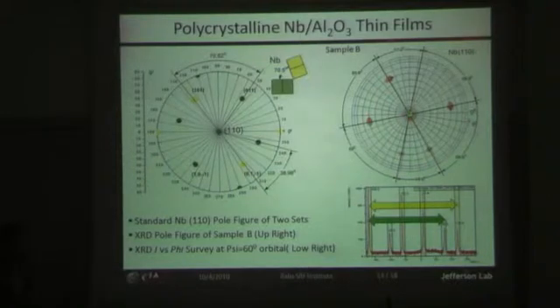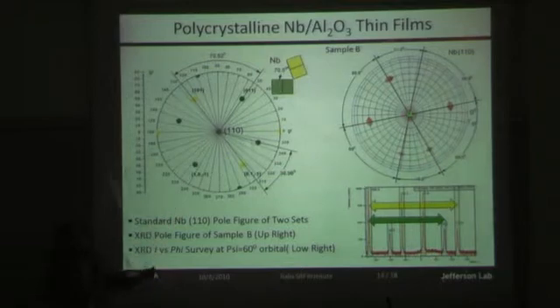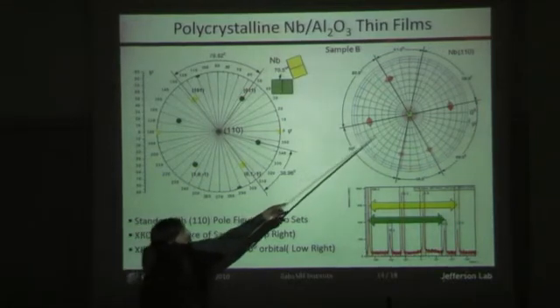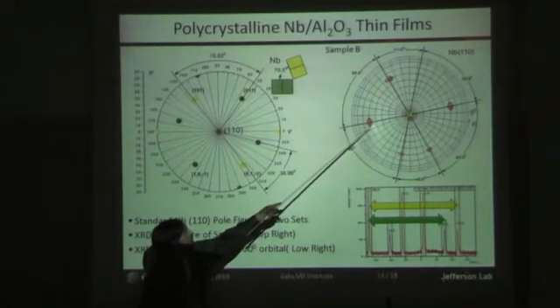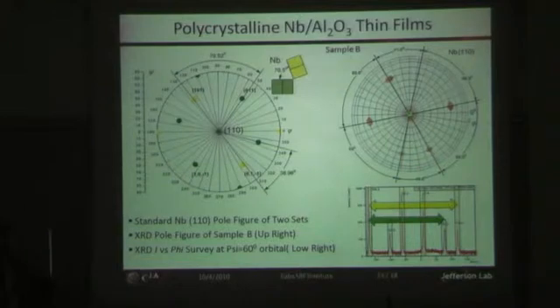At lower substrate temperatures, we were observing polycrystalline films. At first this was very confusing because, as you can see, two of the poles tend to overlap. We were seeing a hexagonal structure appear to come out of a cubic system, which didn't quite make sense. Then we realized that two of the poles are overlapping, giving us an elongated pole, and that we are actually observing a polycrystalline phenomenon where we have two domains of 110 growing preferentially on a given substrate.